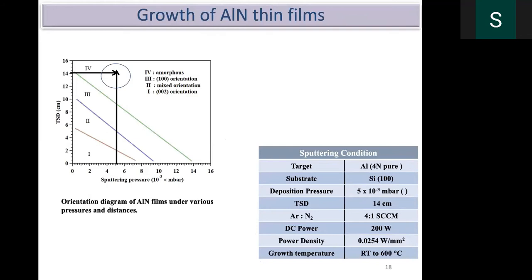And everybody wants to know how to grow the aluminum nitride. In particular, we have varied the deposition pressure and target to substrate distance, all those things. But just here, for our understanding, we kept it at one particular pressure, 5.6. And if you change the target to substrate distance, you will see different kinds of growth. Particularly if you go beyond this line, all are amorphous alumina only. You can get that wherever you deposit, either if you go to higher pressure, I mean this range, and higher target to substrate distance.